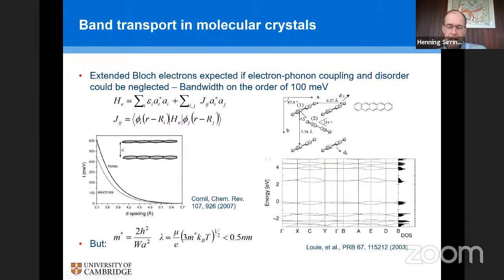You're looking at the molecule here along the long molecular axis, so it's a projection along the long molecular axis, and you can see how these individual molecules stack with respect to each other in this characteristic herringbone stacking. But it's essentially a periodic arrangement of molecules, and you can think of that similarly to a periodic arrangement of atoms, and you can define Bloch states that are derived not from atomic orbitals, but in this case from those pi molecular orbitals similar to those of the individual benzene rings. And then you can think of a band structure forming.